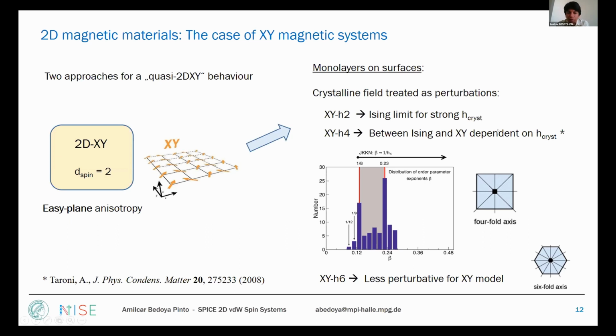I want to point out there's also a very nice review by Andrea Taroni while he was still doing research. He made a compendium of these materials and found out that, depending on the crystal field, the critical exponents will oscillate between the Ising and the XY regime. He treated it mostly for the fourfold axis type, because this is the more ubiquitous system among crystalline substrates used for monolayer growth. And last but not least, we have the XY-H6, which would be a hexagonal crystal field. According to theory, this is the least perturbative for the XY model.